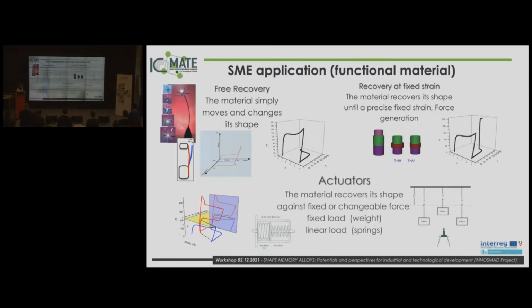The last possibility to use the shape memory effect is in actuation devices. The material recovers its initial shape against a changeable force. For example, the principal theoretical example is the recovery against weight. In this case, the wire in austenitic phase, by applying a load, deforms in the martensitic phase, and then when we heat the wire, constrained, it reduces its length and then moves the weight. This is the theoretical example of recovery with fixed force.